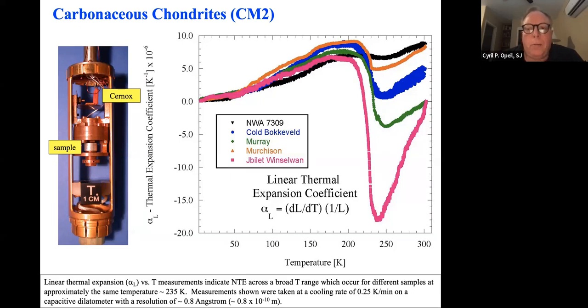But then all of a sudden you have this enormous drop. Now, what's important to realize is that the drops of all of these materials happen at around 235 Kelvin. That's essentially the midway peak here, around 235. The variance between the Jbilet Winselwan and, let's say, the NWA 7309 in terms of the depth probably has to do with texturing, how the material is changing, or perhaps even some weathering.